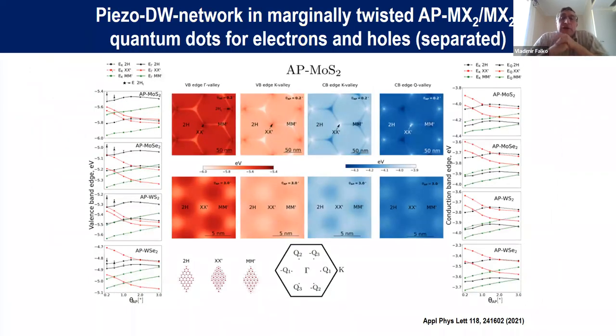So what we did with this, we used that together with the modulation of the interlayer hybridization of band edges for different relevant parts, for the local minima and maxima of the conduction band and valence band, respectively. And we had to do that because, as I mentioned before, the hybridization between the band edges in the two layers is the strongest around the gamma point. That's where electrons have less problem to tunnel from one layer to another. And as a result, when we look at different parts of the band structure of the Brillouin zone, we have different answers about what happens with the band edges. For example, for the valence band, systematically for TMDs, maybe except for tungsten diselenide, we get the band edge for the valence band at the 2H stacking domains.